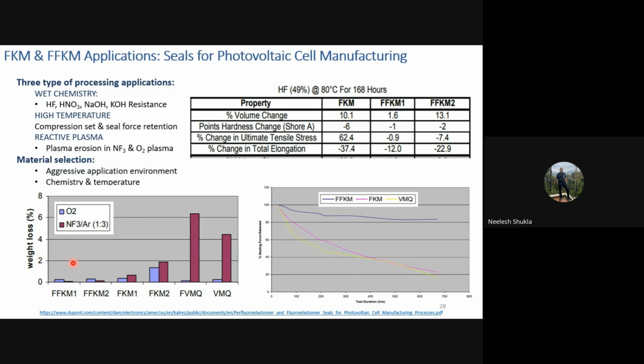Then the second application is weight loss upon plasma erosion. Once the materials are exposed to plasma, it will have an impact on their properties, and there will be weight loss. But that is observed very little in the case of the fluoroelastomer FFKM, as compared to fluorosilicones and silicones. Once again, the last application is where we are talking about high temperature and comparing the sealing force retention. That's where the perfluoroelastomer FFKM performs much better than the other sealing materials.